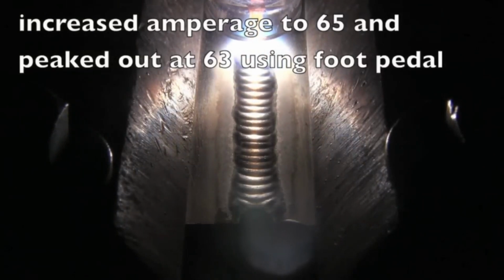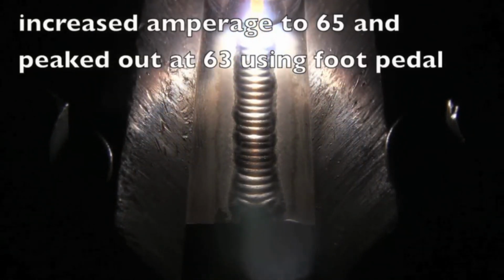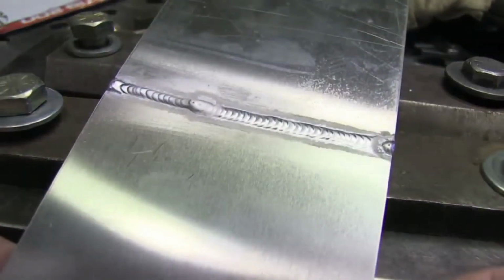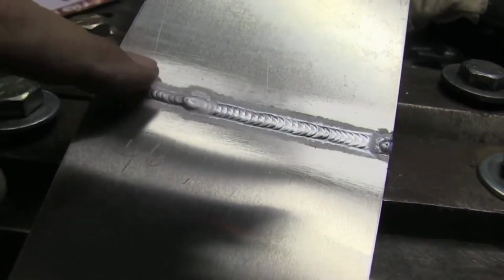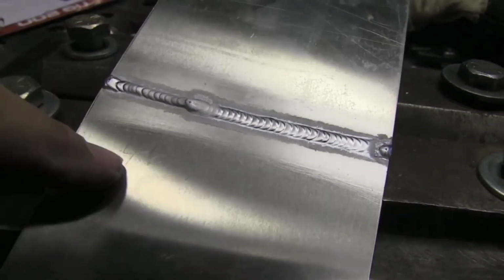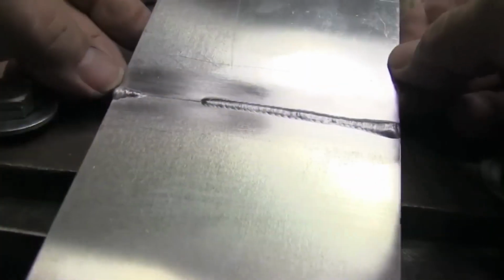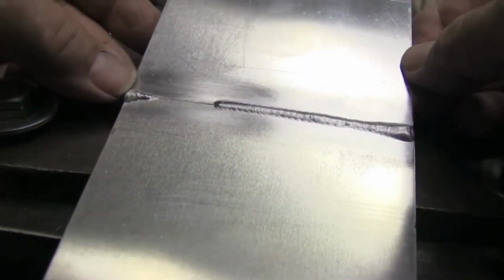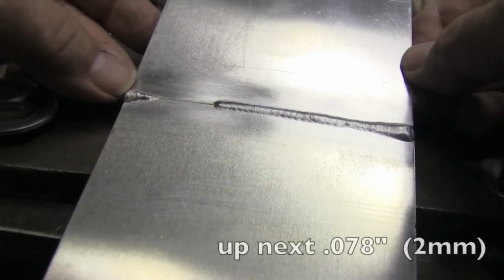So if you have chill blocks or anything like that, and I actually needed a little bit of chill, small pieces of aluminum like this get saturated with heat really quickly. All right, there's the cold part. You can see it mic'd out at 46 thousandths. No penetration there, or very little, only when I got started. And then when I increased the amperage, much better.